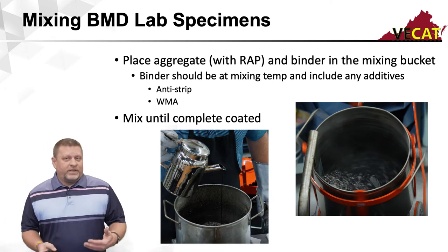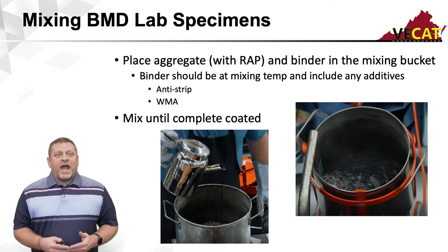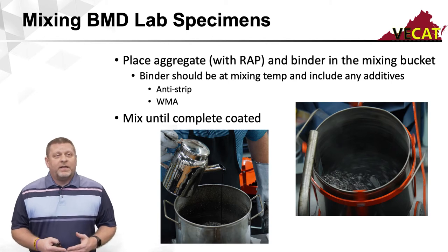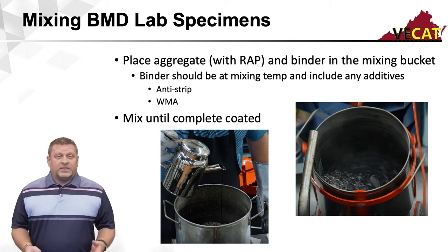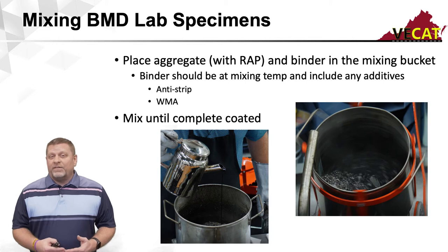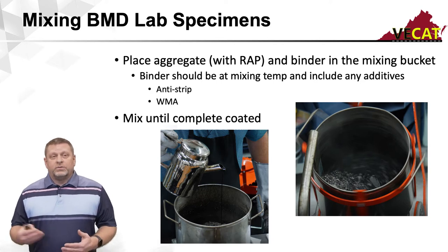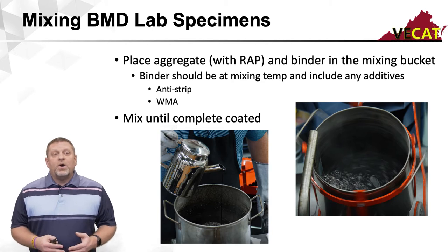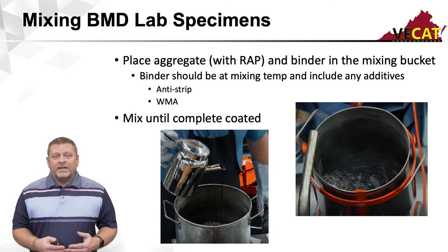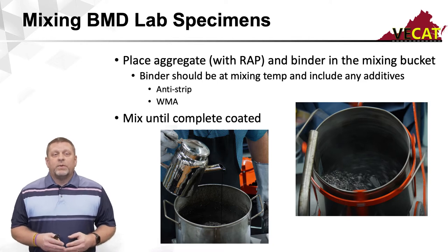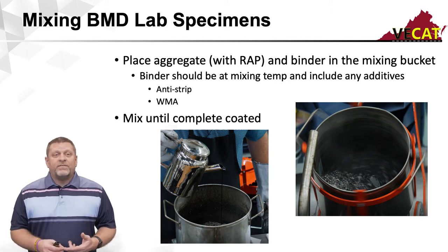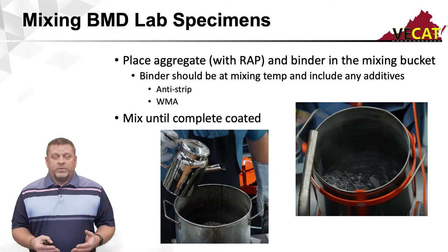When everything is up to temperature and we're ready to mix, we place the aggregate with the RAP and the binder in a mixing bucket. One important thing to note: when you're mixing your performance or BMD specimens, it's important that any additive you may be using be included in this binder. With these performance tests, we've found that certain additives can influence results. So we want to make sure all additives — whether an antistrip or even a warm mix additive — are included in your binder when mixing your performance test specimens.